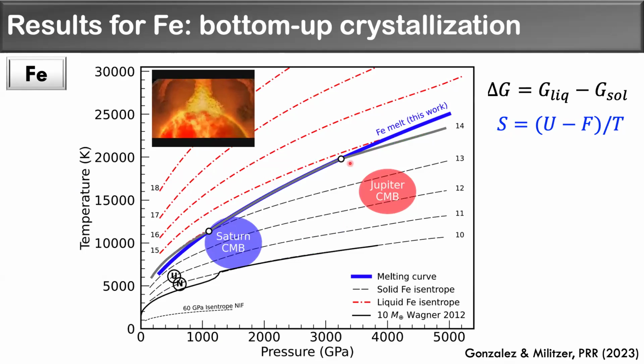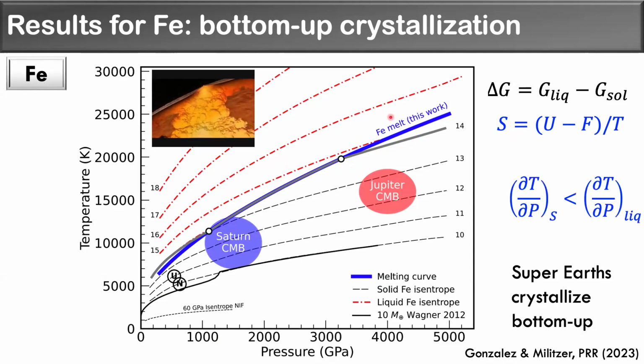And as you can see, the adiabats are shallower than the melting line, which again implies bottom-up crystallization. It starts crystallizing from the highest pressures first, at the intersection. And they represent convective regions of the planet, not like the mantle. In this case, it is the core that is convecting, and it's represented by each of these planetary adiabats. So we conclude that the super-Earths that are in this regime of really, really high pressures crystallize the same way as in the Earth, from bottom-up crystallization.